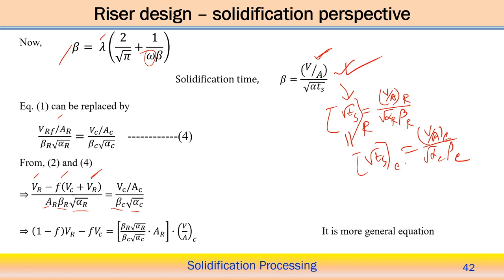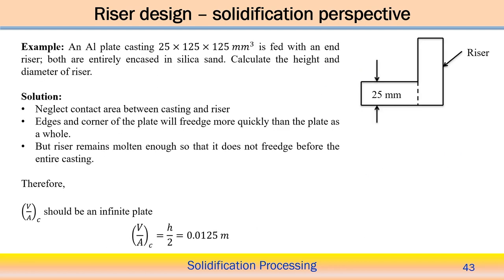So, 1 minus f into VR minus f into VC, equal to, we put on this other side, beta R square root of alpha R over beta C square root of alpha C into AR into V by area of the casting. So this is actually a more general equation, taking care of the volumetric shrinkage during the solidification process. If we solve this equation in different ways, we can get the specific dimension for the riser. So we can utilize this equation with an example also.